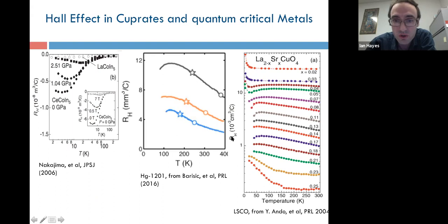So most cuprates show a strong temperature dependence, usually an enhancement, but sometimes it's a change in sign of the Hall coefficient that is strongest near optimal doping. And this isn't even limited to just high Tc materials. Other unconventional or quantum critical superconductors show something like this. So CeCoIn5, I have an example over here on the left, shows a strong change in RH that is strongly associated with just the sort of critical region and highest Tc. So this does seem to be a consistent feature of the superconducting state, or so I should say, superconducting materials in a broad class of compounds.